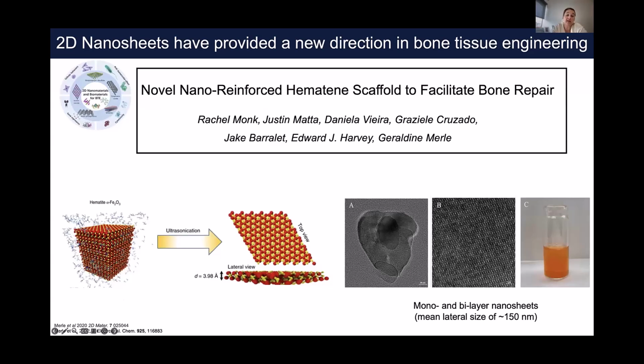So what we did, we took hematite. It's very cheap. It's like a bulk piece of iron oxide. And we developed a system to scale up the production of these two-dimensional sheets of iron oxide. So here you have some transmission electron microscopy. So imagine it's really, really small material. It's like 0.5 nanometer, so it's really tiny. And you can see, this is like 1 or 2 layers of sheets of iron oxide. And here you have the solution.